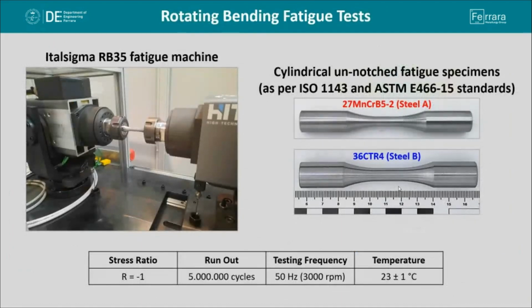On the other side, fatigue specimens underwent rotating bending fatigue tests according to the parameters included in the present slide. So the stress ratio was set to -1, while the run-out limit was set to 5 million cycles.